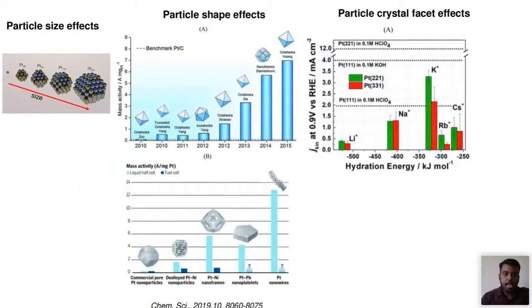And particle size effect. By controlling the size of the particle from 1 nanometer to 100 nanometer, always if you have a smaller size particle, you will have a higher electrochemical surface area and more number of active sites that will increase your activity. And based on the shape, like octahedra to nanoframes perform better than the solid particles.